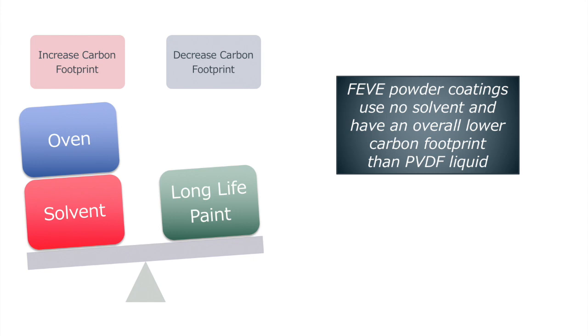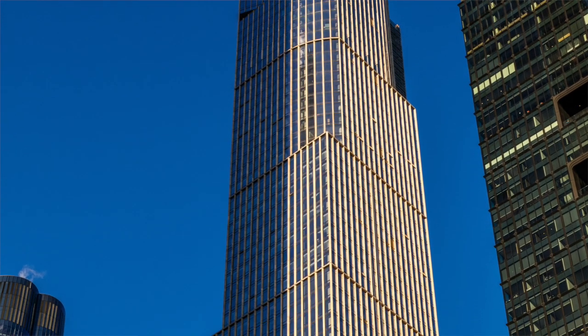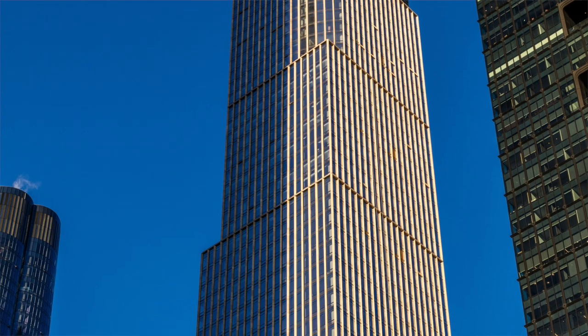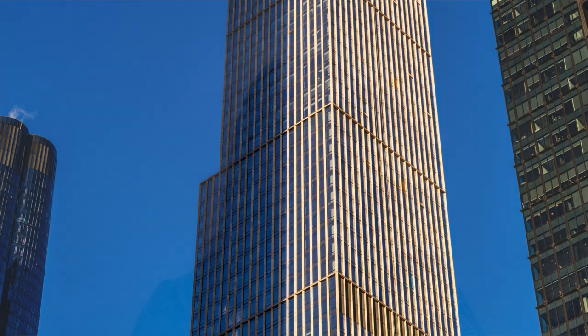FEVE powder coatings also cure at lower temperatures than PVDF solvent systems, and that also reduces the impact of the carbon footprint. And finally, with powder coatings, you have the ability to reclaim the powder. So when you're spraying and applying the powder to a part, any of those powder particles that do not get onto the part, you can actually reclaim those and reuse those. So the transfer efficiency of powder is much higher than traditional solvent-based systems. And so all those things, the lack of organic solvents, the lower oven cure temperatures, and also the reclaimability or recyclability are all things that can impact and reduce that overall carbon footprint of the coating system.